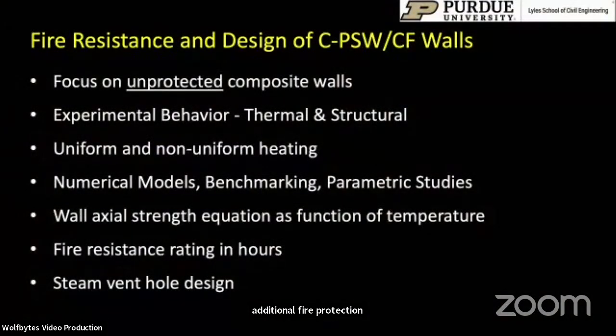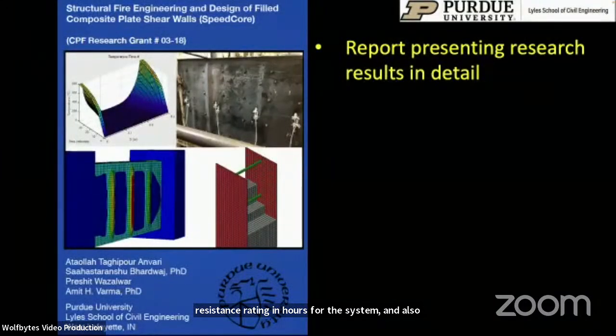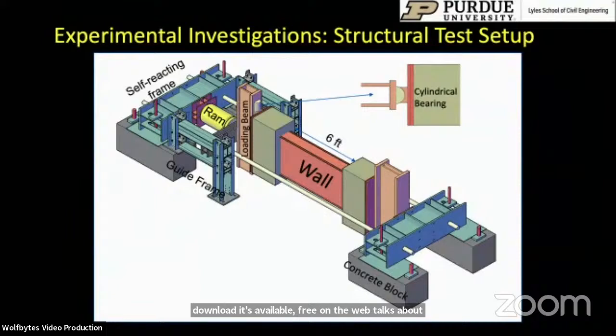We conducted experimental tests, which included looking at the thermal behavior and the structural behavior to both uniform and non-uniform heating. And we developed numerical models that were benchmarked to the experimental data and then used to conduct parametric studies. At the end, we were able to develop wall axial strength equations as a function of temperature and fire resistance rating in hours for the system, and also provide recommendations for steam vent holes for the system. All of this research is summarized in a Charles Pankow Foundation report that you can download. It's available free on the web, talks about all the experimental results and numerical results. And I'll summarize them rather quickly.